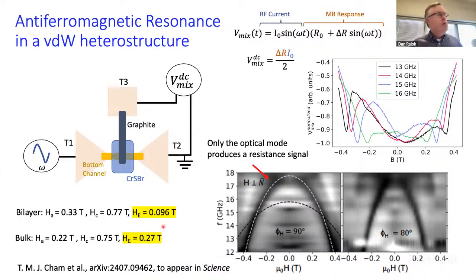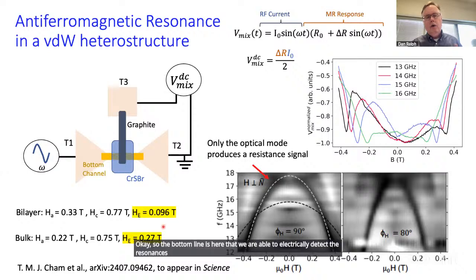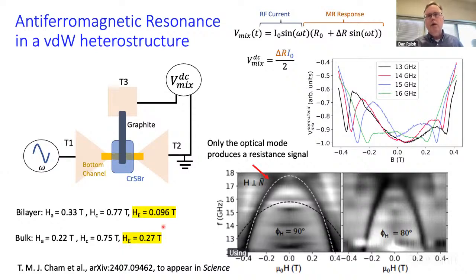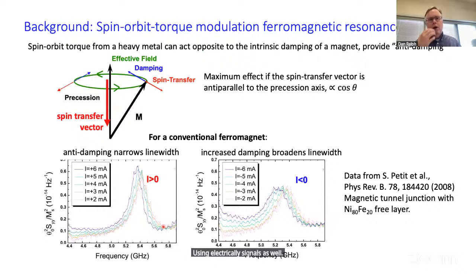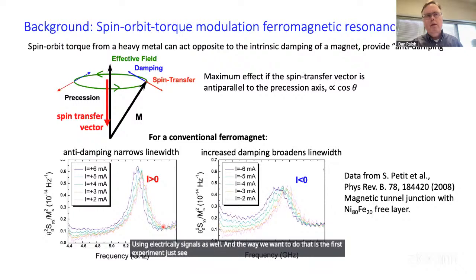Okay, so the bottom line here is that we are able to electrically detect the resonances on small micron scale structures rather than millimeter scale structures with this technique. We can then go on also and see if it's possible to start to try to control the resonances using electrical signals as well. And the way we want to do that, as a first experiment, is just to see if we can control the line width of the resonance with spin transfer torque coming from current in this platinum telluride channel underneath the chromium sulfur bromide.